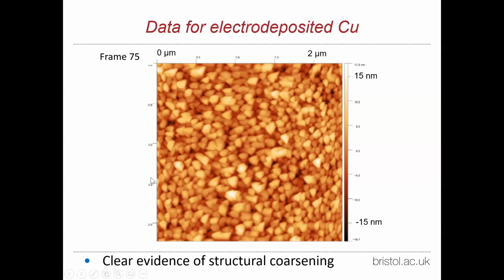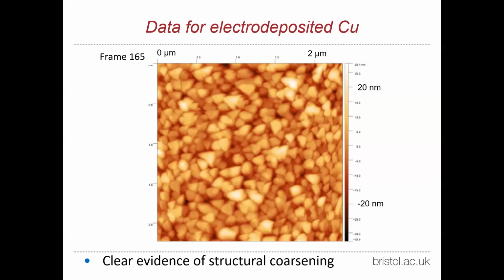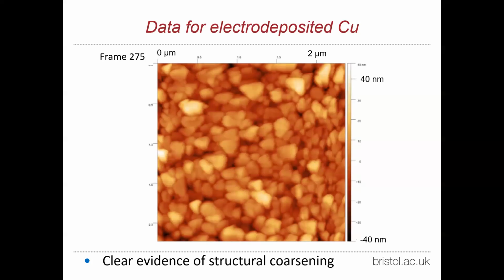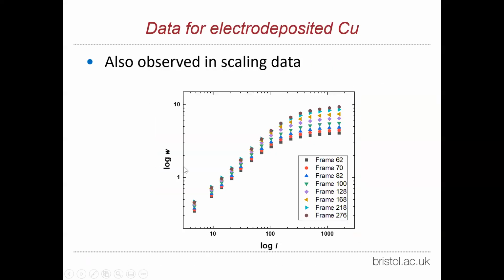Here you see a snapshot from the early stage, fine grains. Now a little bit less fine. Now really quite coarse grains. So you can see it from the image. You can also see it from the scaling data, because the knee, the bend, moves from this position out to this position. That tells you that the grain size is increasing.